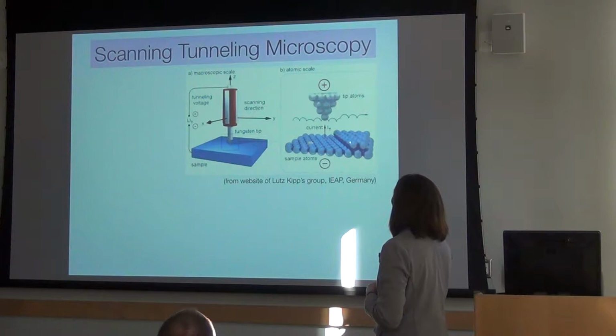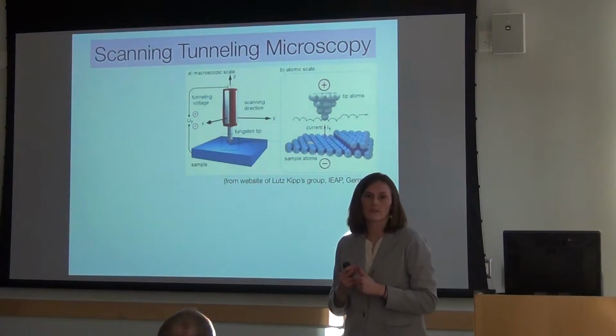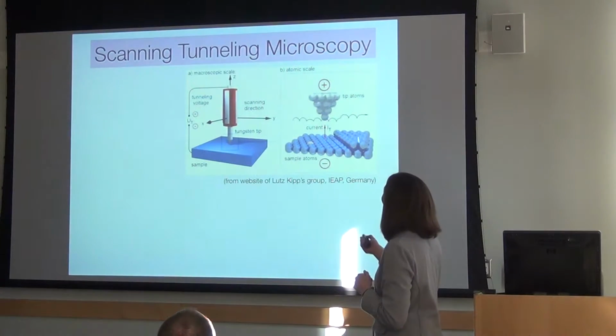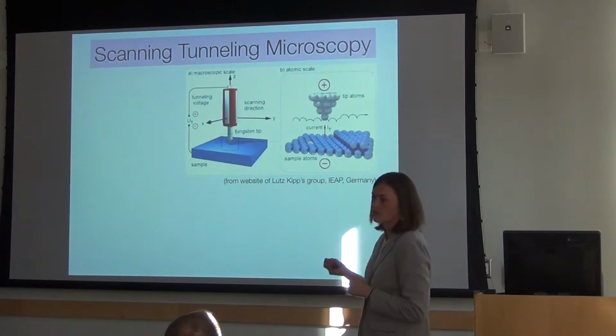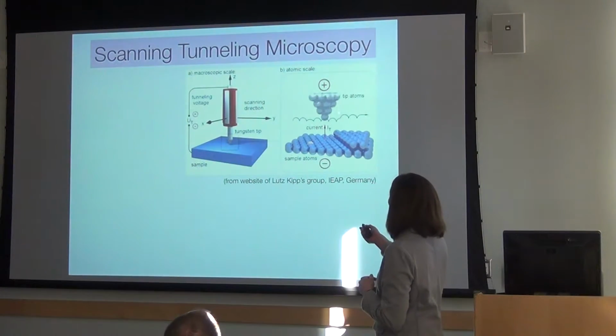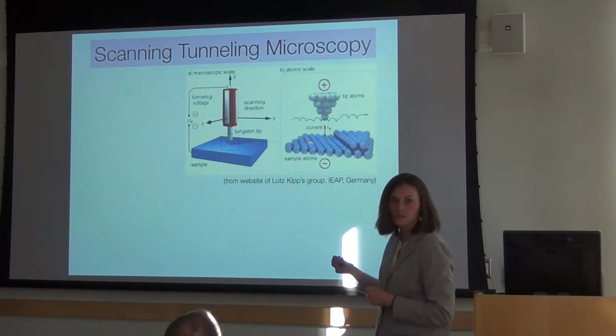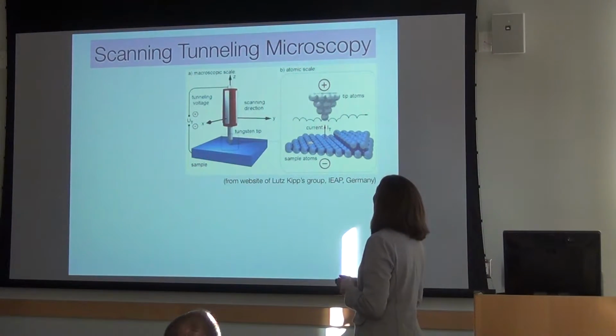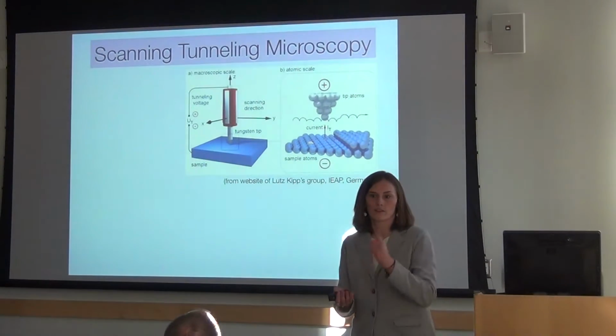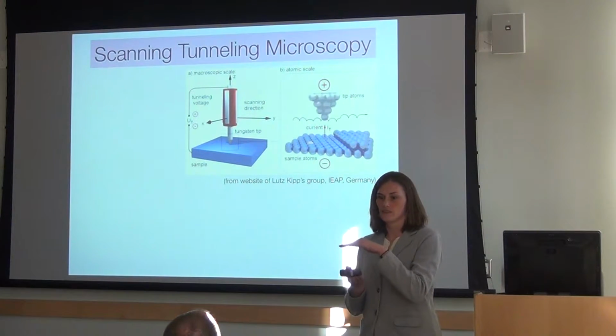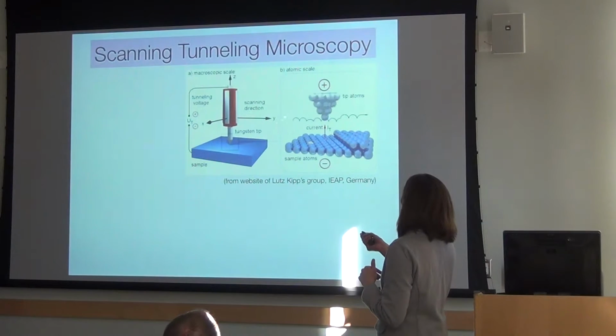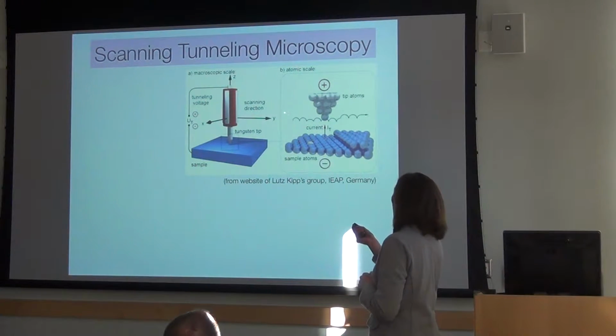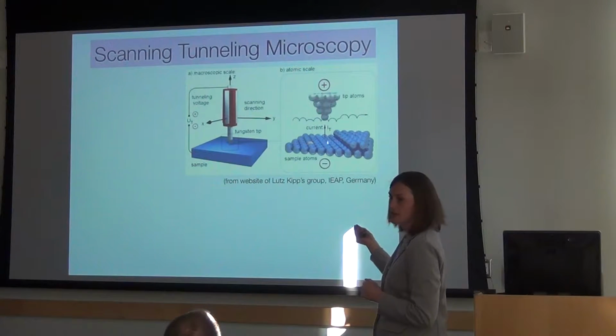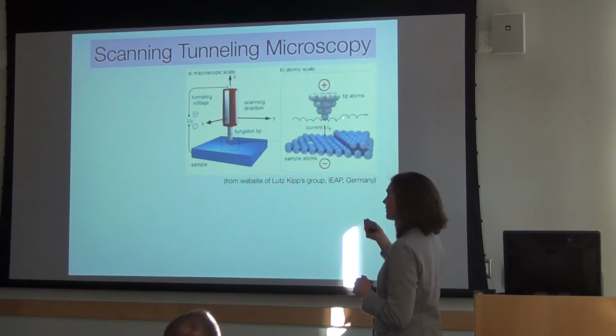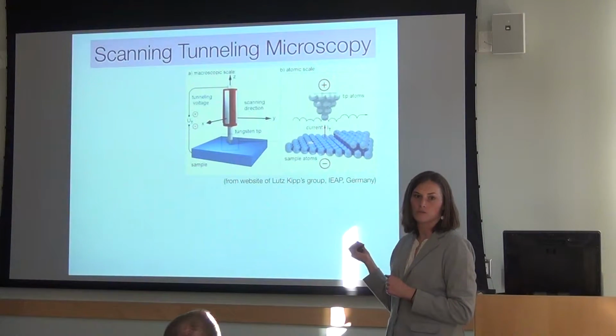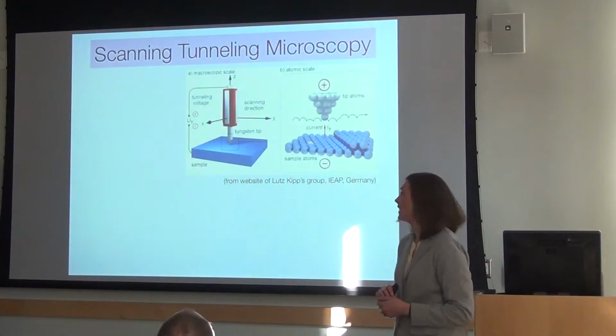On an atomic scale, what you're using is quantum tunneling of electrons to measure, I'll say, the distance to the surface in this case. You have a tunnel junction between the tip, which is made up of atoms, and the surface, which is made up of atoms. And that tunneling current, the probability of electrons tunneling across that gap, depends exponentially on the distance to the surface. So that means that if you get this tip close enough to the surface, as you move it across these atoms, the tunneling current is going to go up and down and up and down, depending on how close the surface atoms are to the tip. So that's why you can have such high resolution of atoms on surfaces. Obviously, it's a little bit more complicated than that.